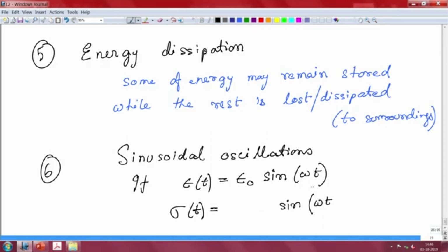We had seen that for an elastic body the two are supposed to remain in phase, whereas for a viscous fluid there was going to be pi by 2 difference, but now you are not going to have that. Instead, you are going to have some other difference where delta is not pi by 2, it is some other value. And here in the numerator, in the amplitude part, you are again going to have a constant part and something else that depends upon omega, the imposed frequency. Right.